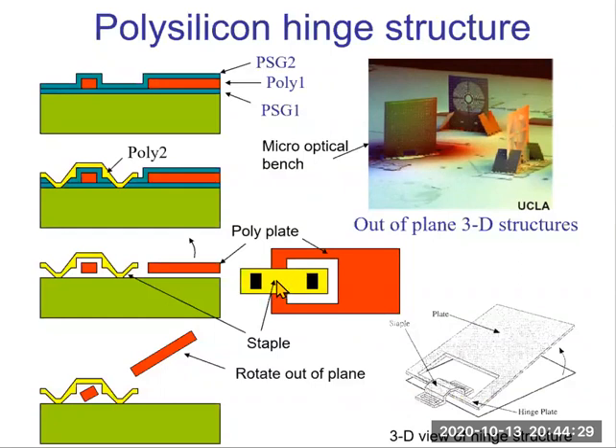This yellow pattern stands for the staple. This yellow pattern represents the staple. This red pattern represents the polysilicon plate. So we can say this plate is made from poly 1. The staple is made of poly 2, this yellow layer. And the staple anchors to the substrate. So these two areas are patterned in this step. And then this plate can be rotated out of plane. So we can make some 3D structures based on this hinge structure.